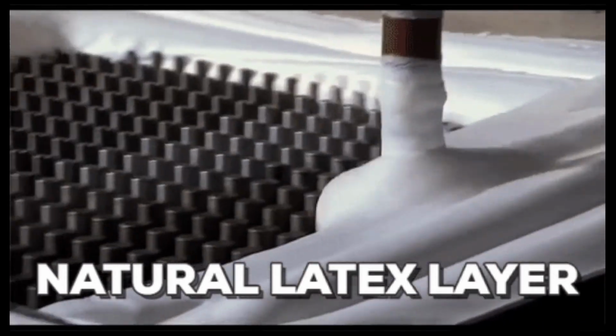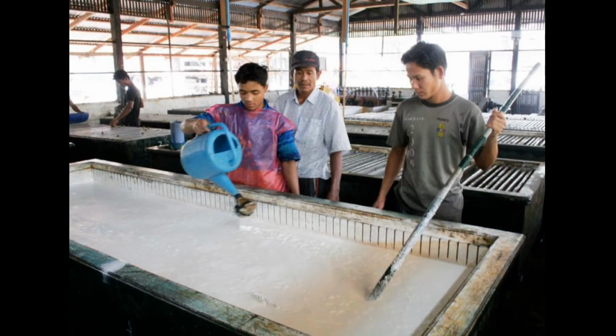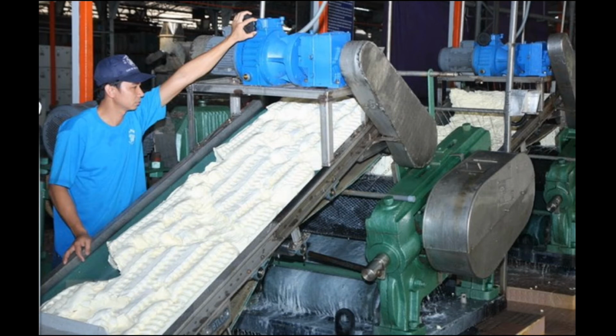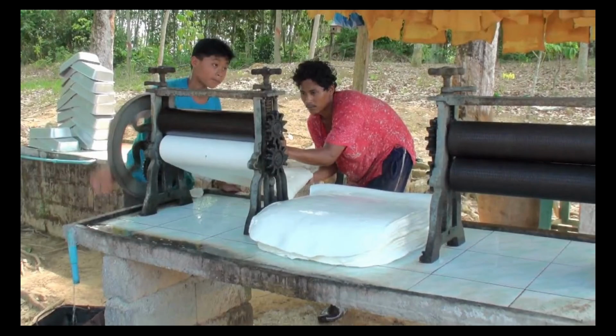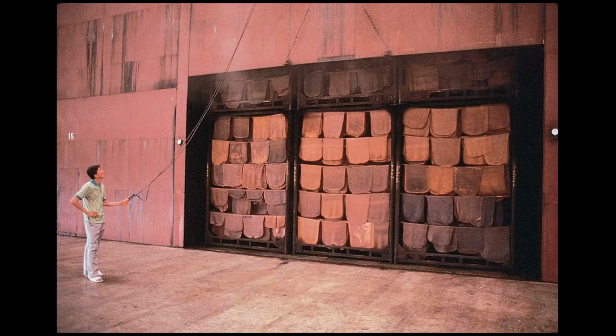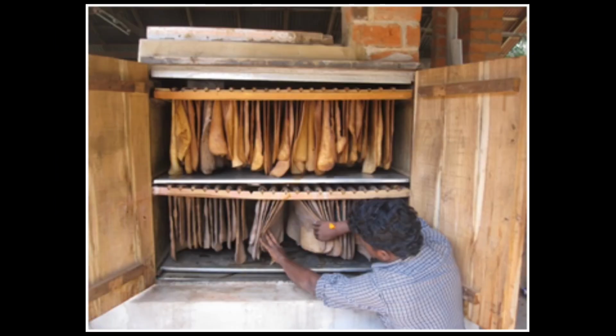When the sieving is done, acid is thereafter added to coagulate the liquid latex. The coagulated crude rubber is fed into rollers to squeeze out the water, thereby forming a sheet of crude rubber. These sheets are dried with hot smoke in order to kill the mold and bacteria that could make it rot.